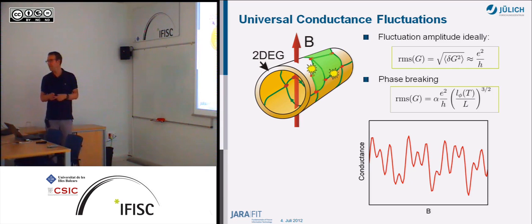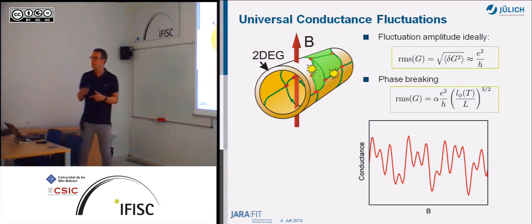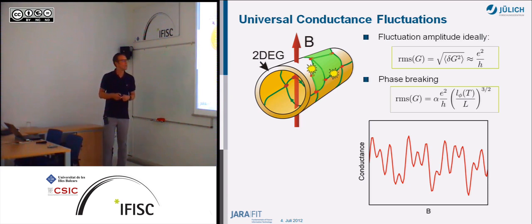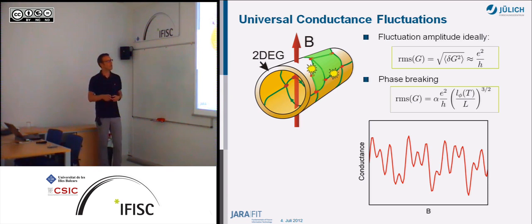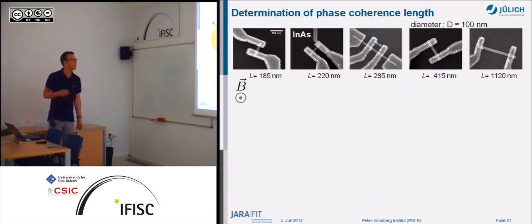But this is only an ideal case. If you have phase breaking in between here somewhere, then this factor is reduced, and this reduction is determined by the phase coherence length. So if you do that the other way around, you can get information. If you look at the RMS here, you can get information about the phase coherence length and study this by looking at the universal conductance fluctuations. So that's what we did here.